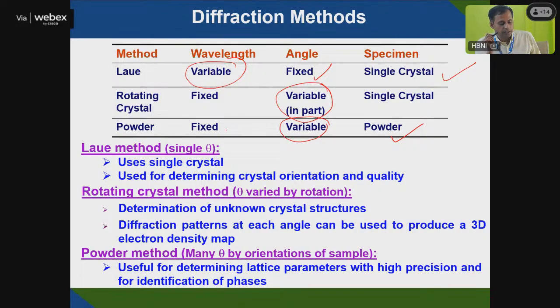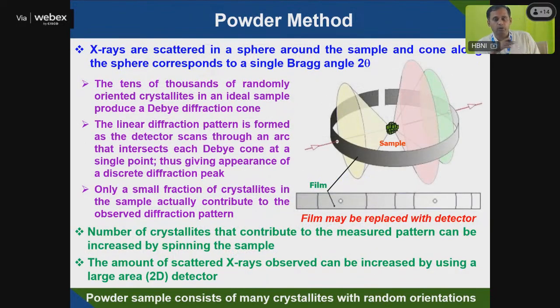So the Laue method is mainly used in single crystals to determine the crystal orientation and quality of the structure. The rotating crystal method is again used for unknown crystal identification. If you have an unknown crystal, you have to go for single crystal XRD to identify that structure. In powder diffraction, there are many orientations. The sample is composed of a polycrystalline material. It's not a single crystal. You have many crystals, and you can use the powder diffraction method for identification of lattice parameters with high precision.